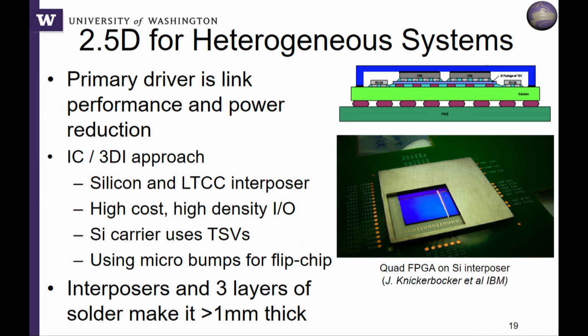So we were able to produce a carrier using silicon technology. We used silicon, and created all the wires between those chips on top of that silicon using traditional techniques. Then we took that module and put it on a co-fired ceramic interposer, and we were able to get a supercomputing type functionality out of that.